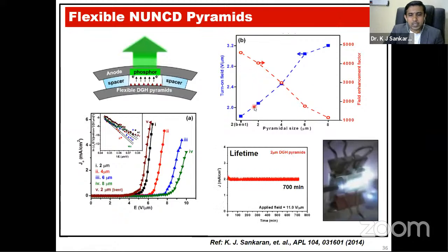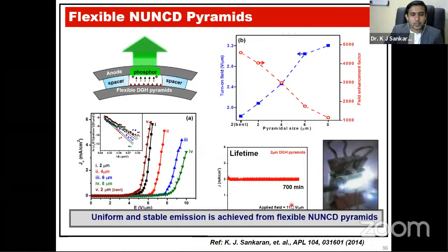We also made a real-time device. This is the field electron emission device with a lifetime of 700 minutes, as compared with carbon nanotubes and graphene, which have only 30 minutes. The diamond materials have very uniform emission without any decay in the current, even in a bending state, with a very low applied voltage and high lifetime stability. So the flexible NUNCD pyramids achieve high lifetime stability with stable emission current even at low applied voltage. Uniform and stable emission is achieved from flexible NUNCD pyramids.